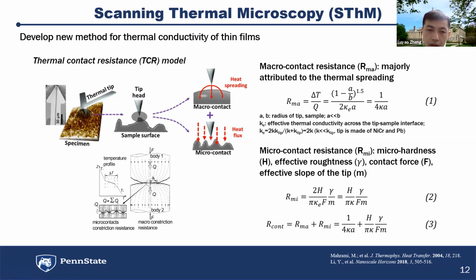So here we set up this model and use these equations to address both the macro contact resistance and the micro contact resistance, based on these two equations. This one is related to the thermal spreading, and this one is more related to the surface conditions of the thin film. There are a lot of parameters involved, but we can address all these parameters from the AFM mapping. And here are the equations. So we get the total thermal contact resistance by equation 3, the sum of these two parts.